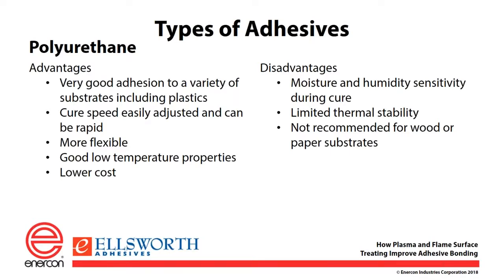However, a major disadvantage of a polyurethane is they are sensitive to moisture and humidity. If you have a substrate that inherently has water in it, it is not usually a good choice, at least for a two-component polyurethane adhesive. They will form bubbles inside your material. In fact, if there's enough water present, they'll foam right up. This is one of the ways they actually make blown foams.